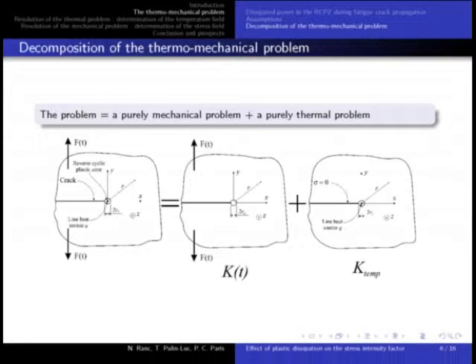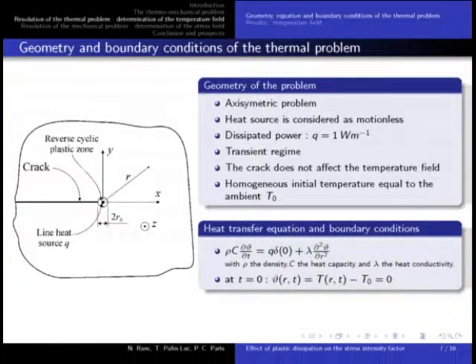What are the boundary conditions? The first important point, the assumption in order to be able to compute the temperature variation field around the crack tip. So from a thermal point of view, the problem is axisymmetric, and the heat source is considered as static or motionless. And we will see that in the equation, the temperature field and the stress intensity factor due to temperature are proportional to the heat source. So we have solved all for the computation with a unit heat flux. But we will see the effect at the end if we consider another value.